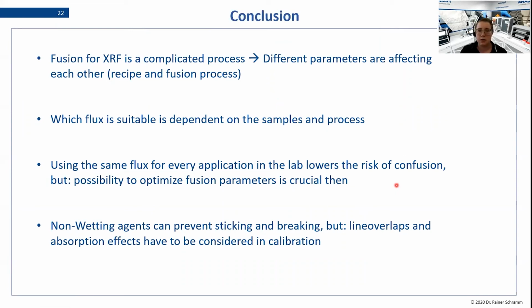There are some laboratories that always use the same flux for each and every application. And that's fine as long as it works, because there's a lower risk of confusion. If you are using another flux for each application that you're doing in your lab, the risk of confusion is way higher. But that also means that your fusion machine or your muffle furnace or whatever you're using to do the fusion has to be optimized, and there has to be the possibility to even optimize it, to go higher with the temperature, to get a better agitation there, and all the things, the cooling, the timing, everything we talked about in the last few slides.